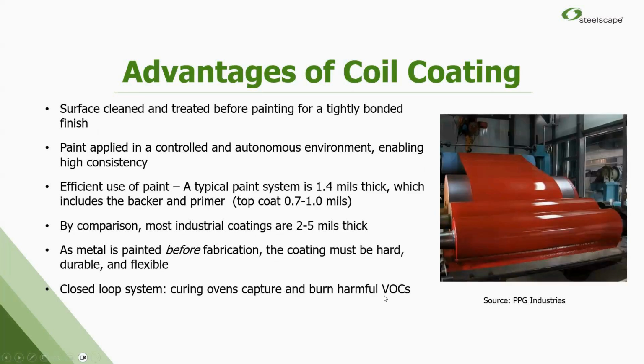The advantages to this process are how tightly controlled it is, how quick it is, very consistent. We can repeat colors and film control over and over and over. It's rapid. We're only using 1.4 mils of paint total. That is thinner than a piece of paper. So it's a very, very thin coating, but we're expecting it to do a lot performance-wise, and we'll get into that later. Most other industrial coatings, painted products are 2 to 5 mils thick, so a very big difference in thickness. And again, it's painted before fabrication, so this paint has to withstand the fabrication process afterwards, as well as go on the outside of a building and hold up for 30, 40, 50 years without much weathering. So there's a lot of science from the paint companies and the coating companies that go into these products.